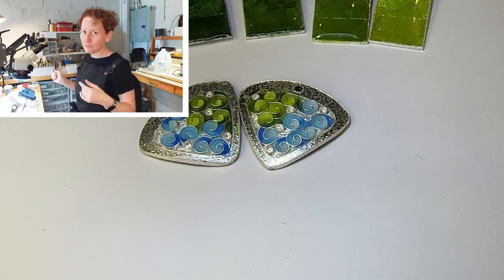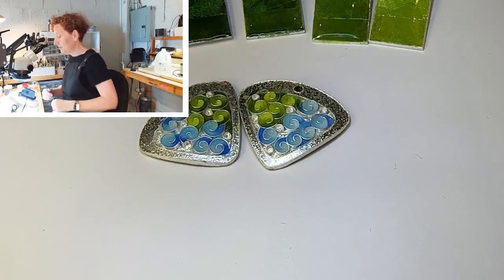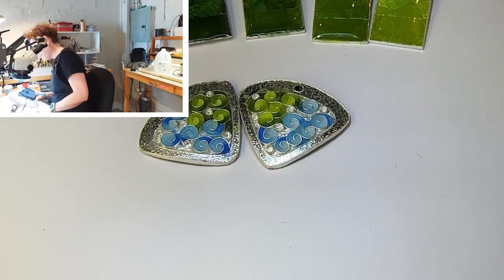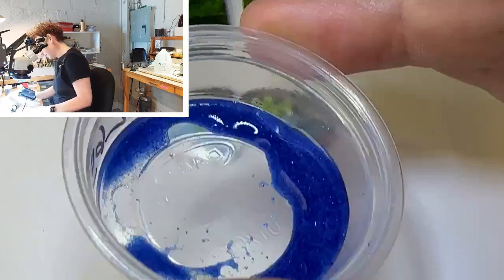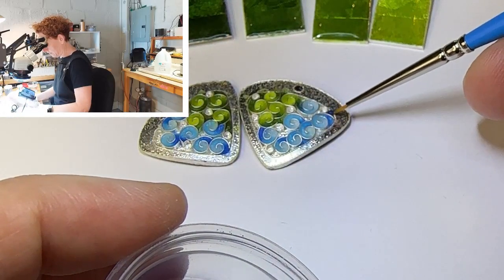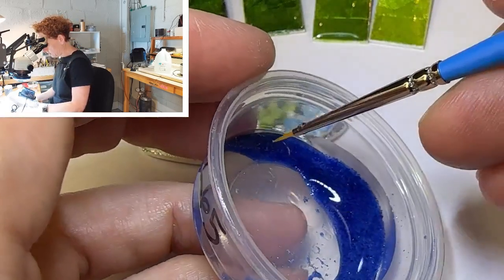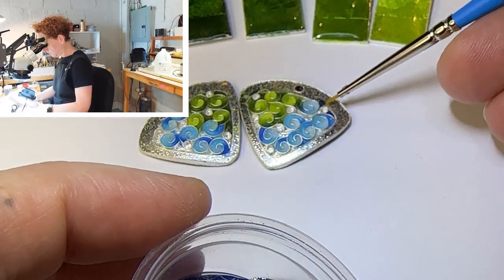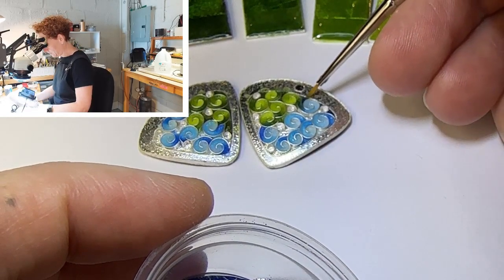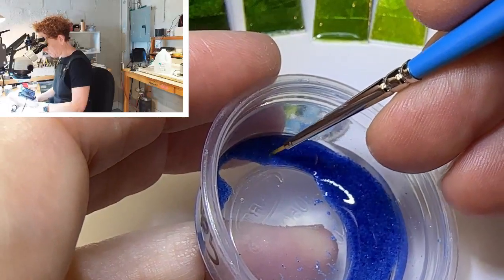But you could blow out your pinks, so your reds will turn brown. You definitely made the right call. Good for you, taking initiative, especially if it was your first class and you didn't really know what to do. But if you have a kiln that doesn't have a temperature controller, it could get hot enough to melt the silver, or if you're enameling on copper, you'll get that eutectic reaction where the silver wires melt into the copper, which is never fun.